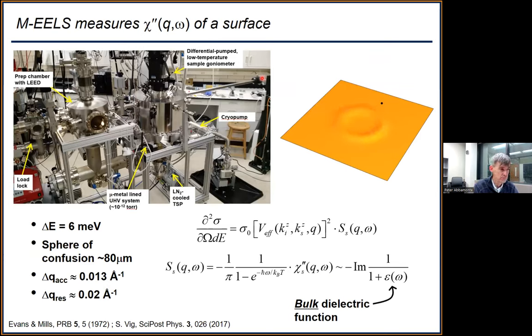So we've been calling this MEELS. It's basically momentum-resolved electron energy loss spectroscopy, which is a fancy word for inelastic electron scattering. I could go through the math, but what's way better is a movie. So let's suppose I take a material and I cleave it, and then I take an electron and shoot it at the surface, and it'll scatter from the surface and make a collective mode. A collective mode could be a plasmon, a phonon, an exciton, it could be anything, but it has to be something that modulates the density. Then I specify the incident energy and momentum of the electron, and I measure the energy and momentum of the scattered electron. And if I see a peak with a certain energy transfer and momentum transfer, I know there has to be a particle there.